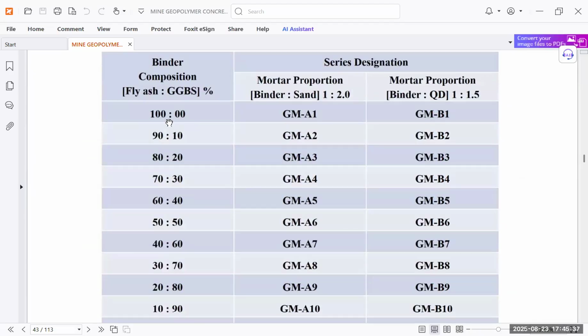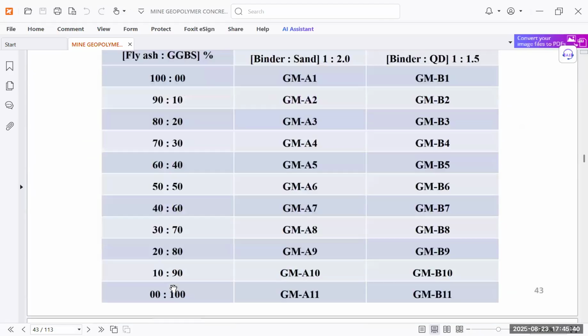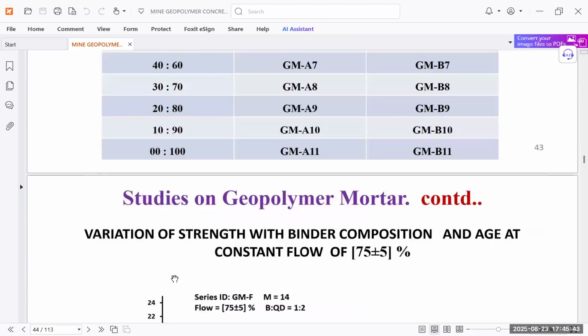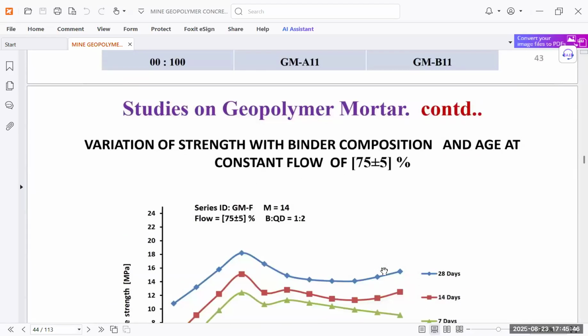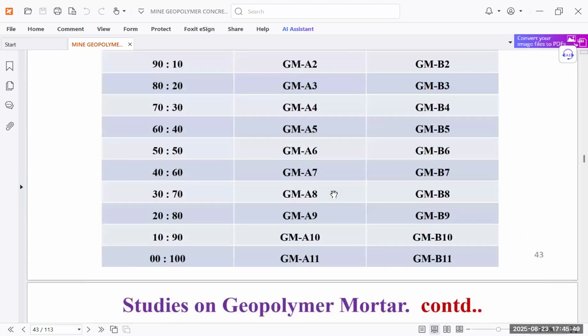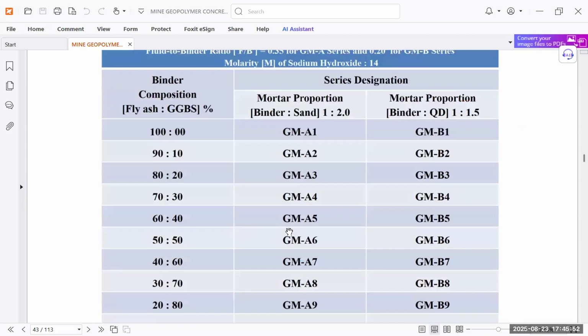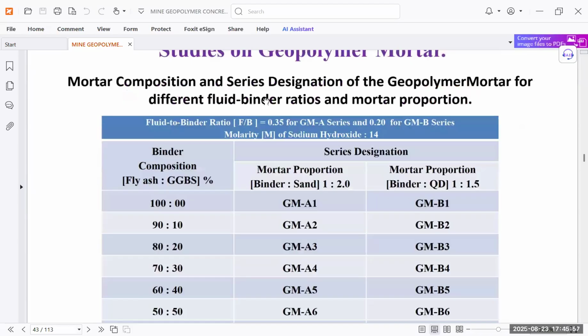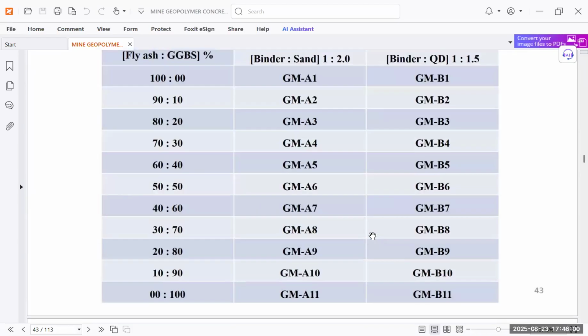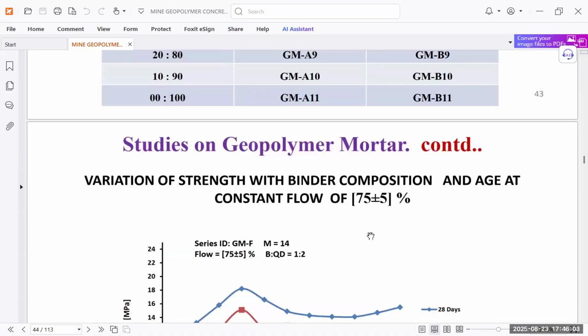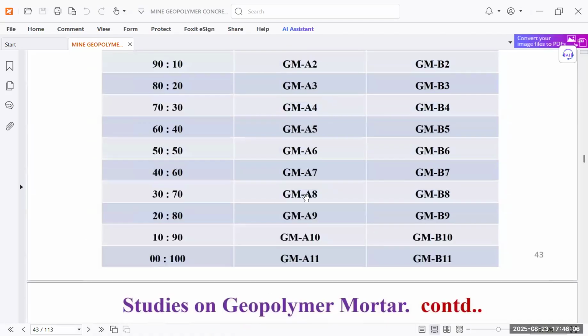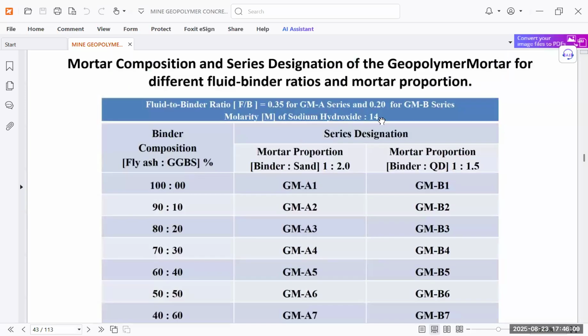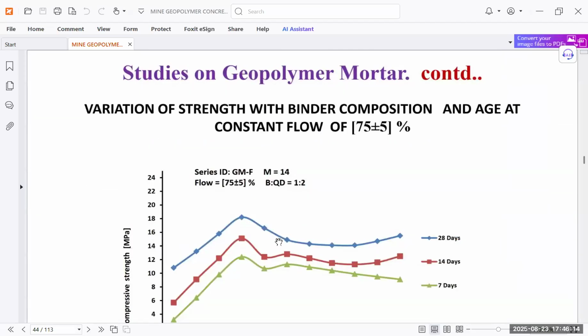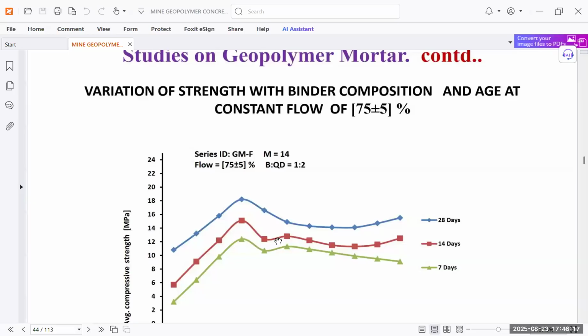These are the compositions we have taken: 100, 90, 70, 30, all different. By playing with these ratios, we can get the different required strengths. As with different cases of RCC mix, geopolymer concrete can give the same type of different results as the binder to cement ratio varies. These are the ways we can get different strengths. Similarly, strength can be obtained by varying the fly ash to GGBS ratio, the molarity, and the fluid to binder ratio. The same way we can get results for geopolymer concrete and geopolymer mortar.